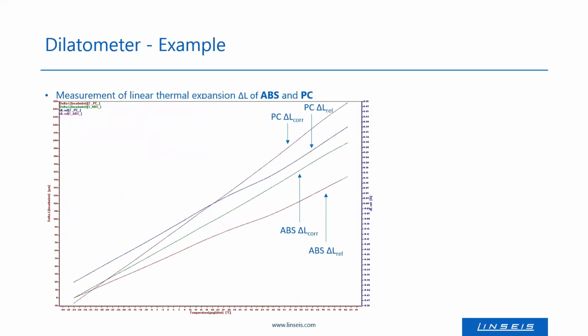Here you see an example of a dilatometer measurement. Here the linear thermal expansion of ABS and PC was measured. So you see here for each a curve which shows the relative linear thermal expansion and the corrected one. The corrected one is just the relative one referred to the size of the sample at room temperature.